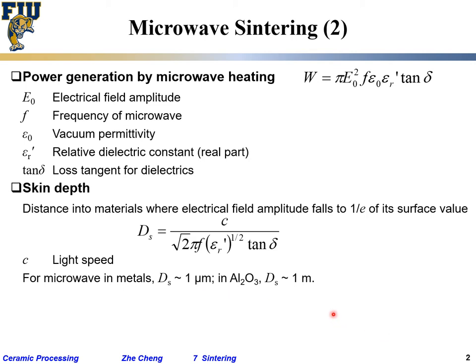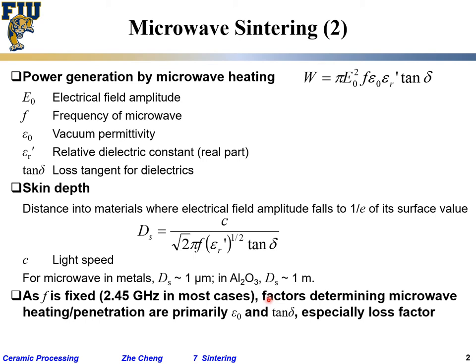In aluminum oxide, the microwave can penetrate pretty deep into the material. Due to FCC communication regulations, microwave generators available for purchase have pretty much fixed frequencies — 2.45 gigahertz is the most common. As a result, the parameters that determine microwave heating are essentially limited to the relative dielectric constant and the loss factor for the material, since vacuum permittivity is a fixed constant.